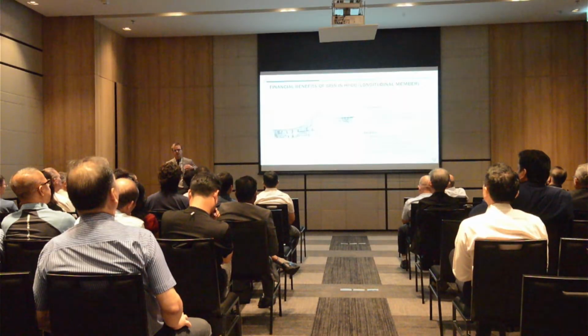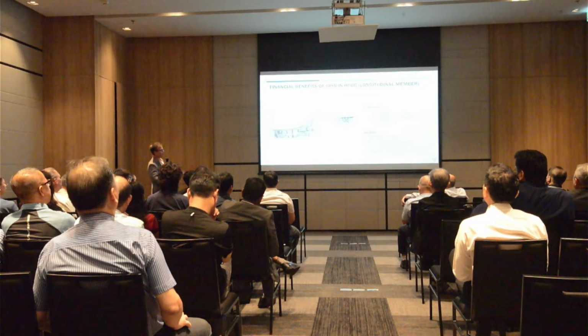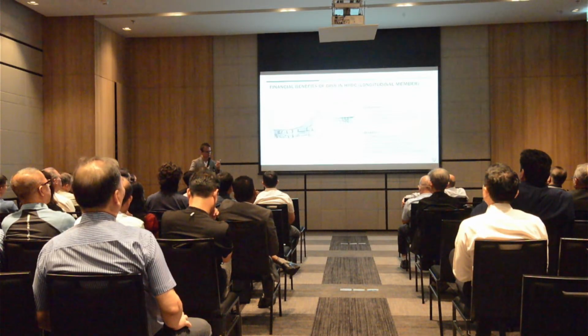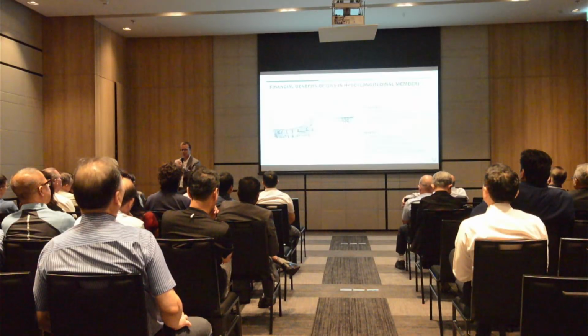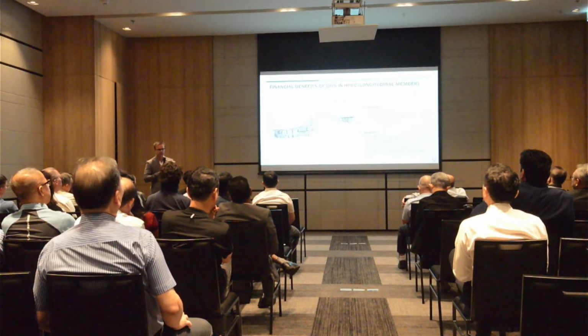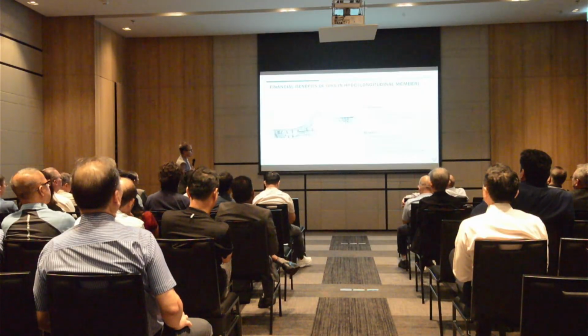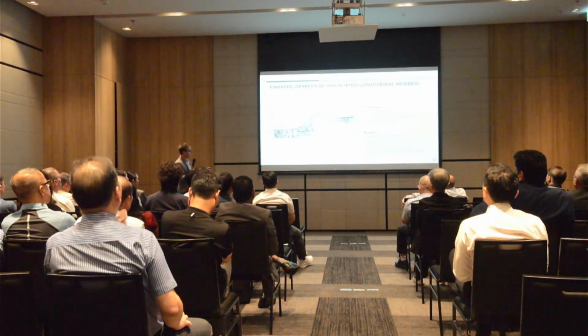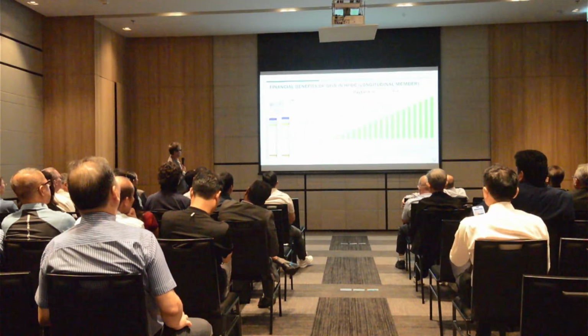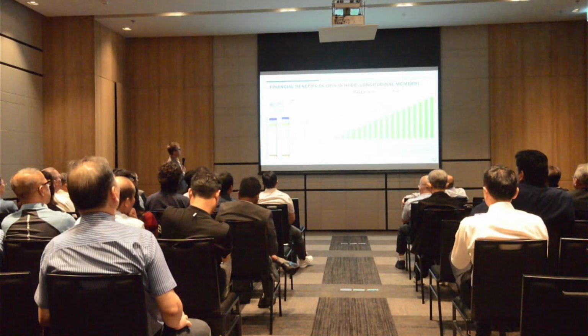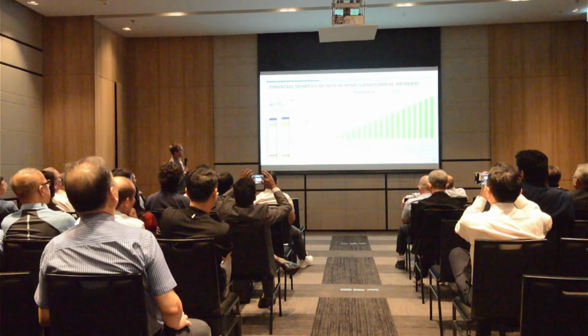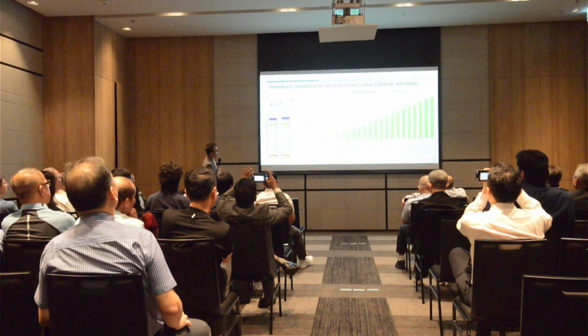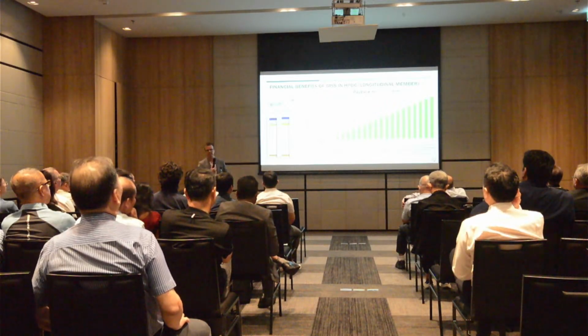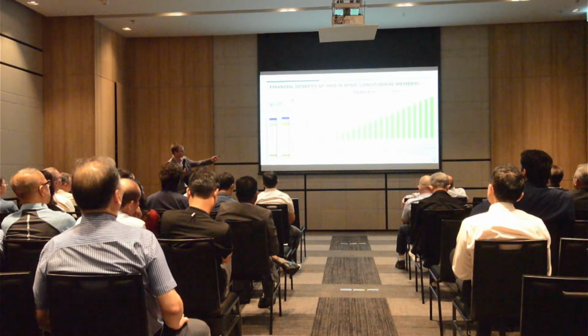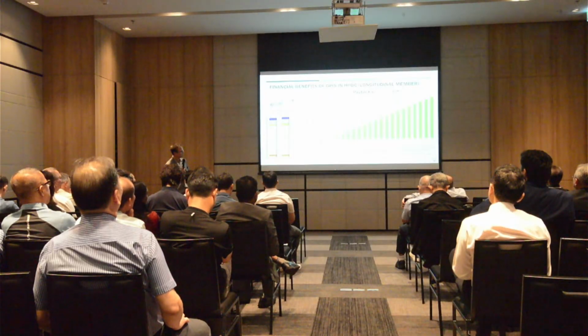I mean, it's a thin-walled structural component, but just on a bigger machine. Less die problems, 2%, and also less problems with the joints where the helicoils have to be put in. So you have to machine, you have to put the helicoils in, and this is always the area where you need attention. And again, here, lower energy, and if you factor this in for this component, you can see it's around 1.7 euros per casting difference. And the investment of like 240,000 is amortized in less than 10 months and gives you a huge amount of savings after the 2 million components.